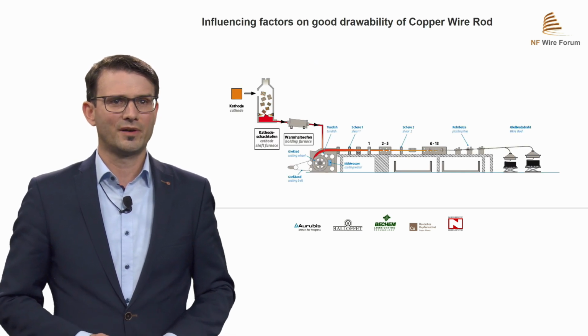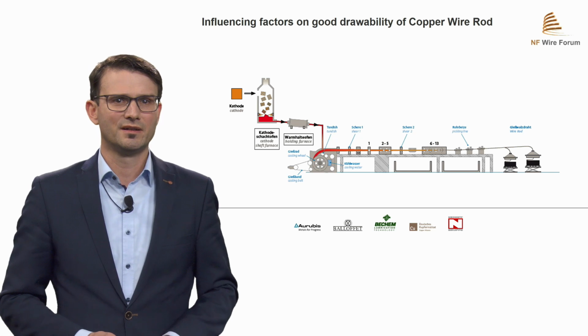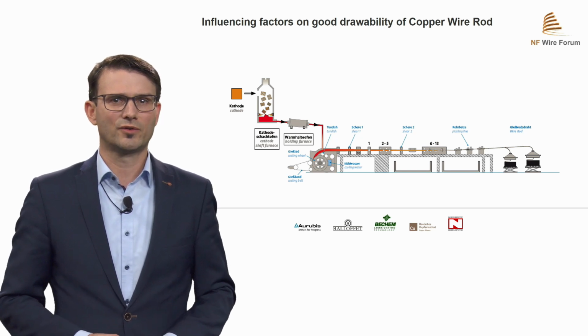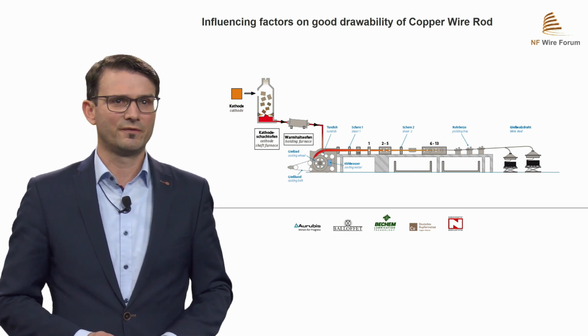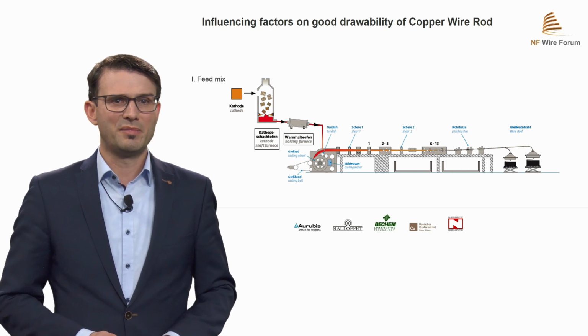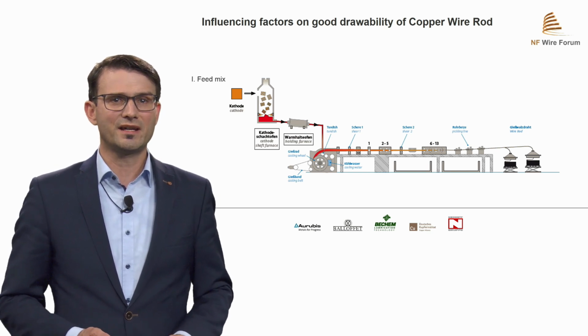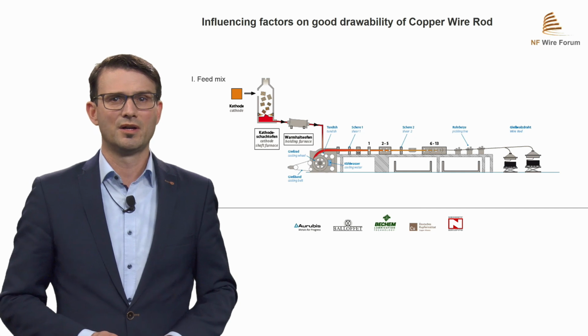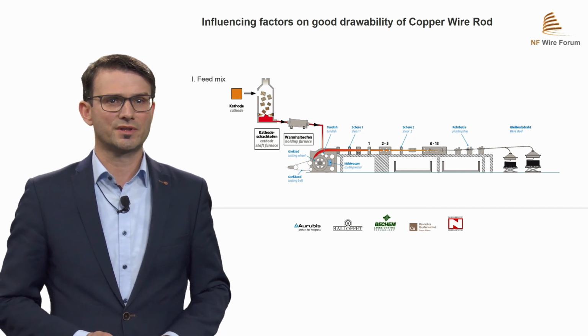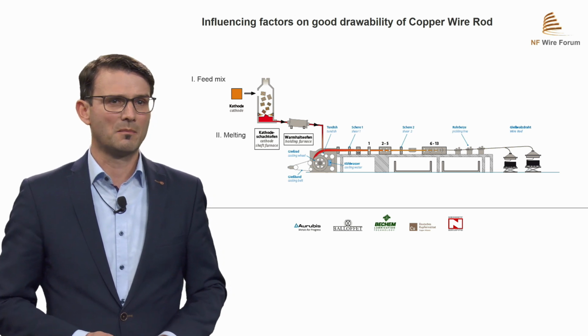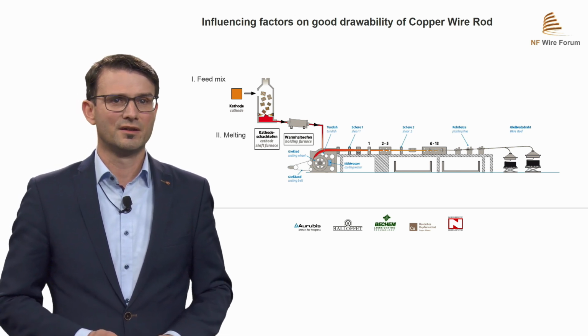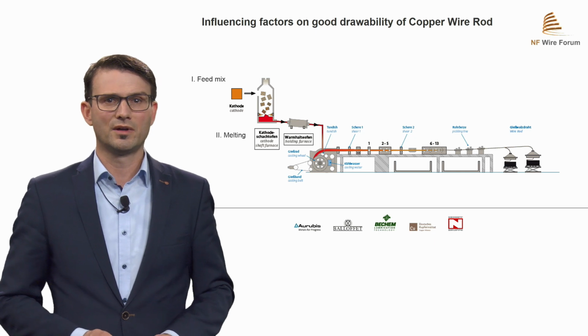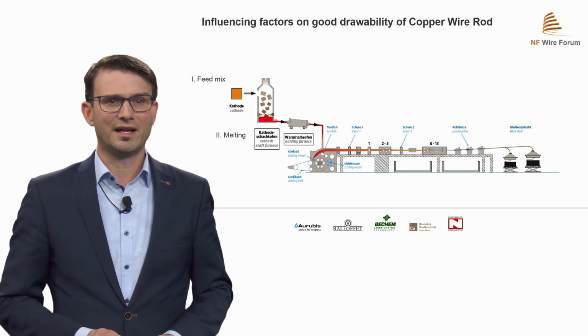There are 5 main process steps influencing the quality of copper wire rod. First, the feed mix: the best feed mix of grade A cathodes to achieve the copper quality which is needed to draw down to different wire diameters. Second, melting of the feed mix: a constant metal flow with the right temperature and gas level to supply the rod line with the needed volume flow rate.